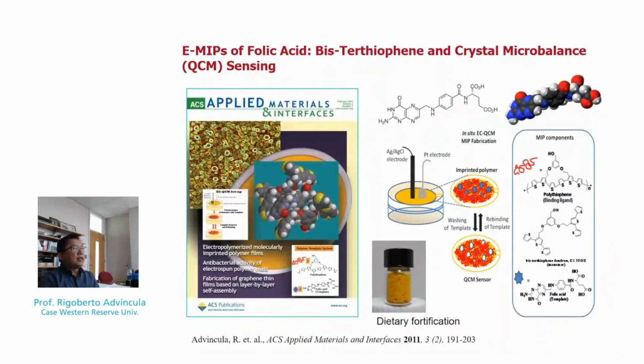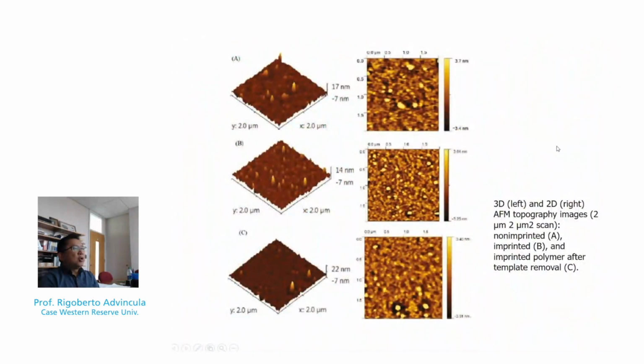Now, finally, in this last example, we actually use quartz crystal microbalance to sense folic acid using this molecular imprinting technique. And to summarize it, and I want to close using an AFM image, we then image the topography of the imprinted and the non-imprinted polymer, or sometimes we would look at before and after sensing, and then we would use AFM to investigate the changes in morphology as the analyte binds to the surface, specifically or non-specifically. And again, referring to the original paper, we discussed further the importance of AFM combined with SPR to get a complete picture of the phenomena or an optimized sensor.